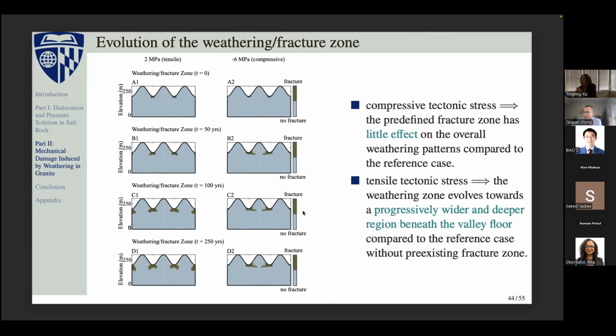And if we insert this pre-existing crack zone, and compare these results with the results from the left side, we can see the influence of this pre-existing crack zone. You can see that under the compressive tectonic stress, this predefined fracture zone has little effect on the overall performance, but for the tensile tectonic stress, it progressively gives us a wider and deeper region beneath the valley floor. So that is a comparison of the cases without the pre-existing fracture zone and with the pre-existing fracture zone.